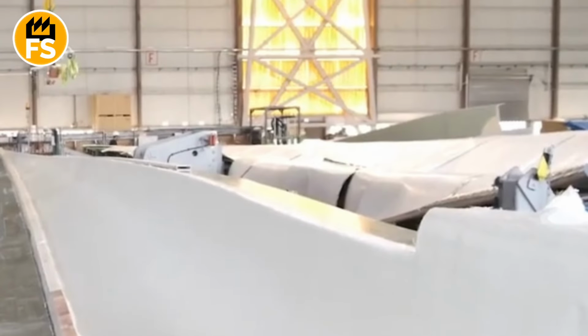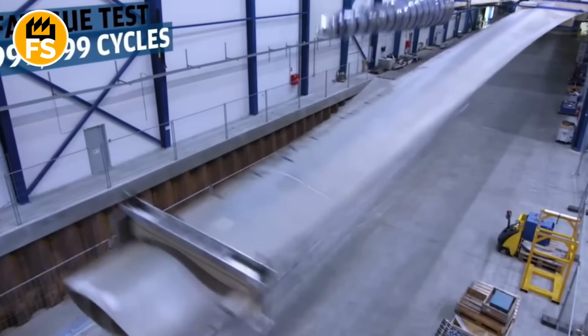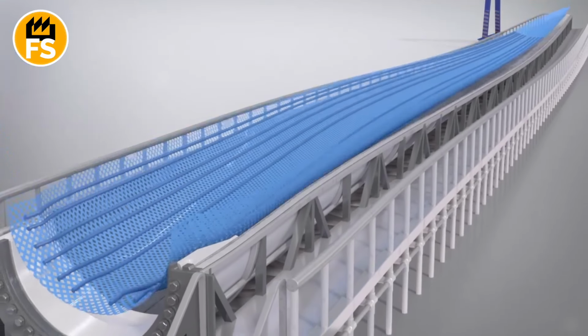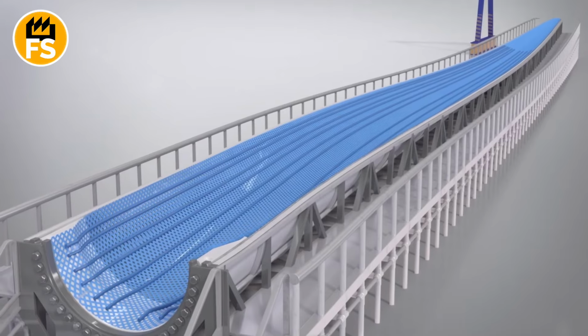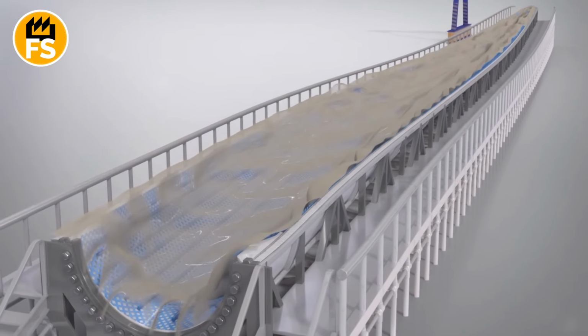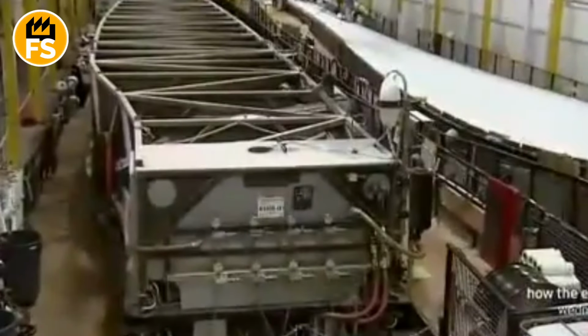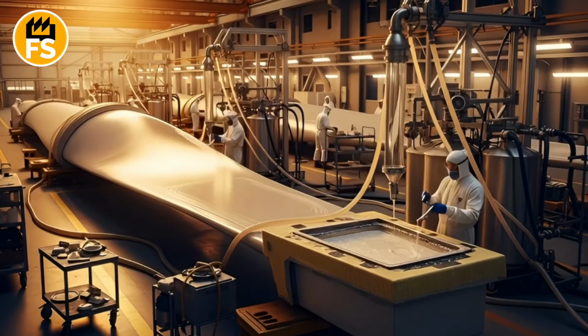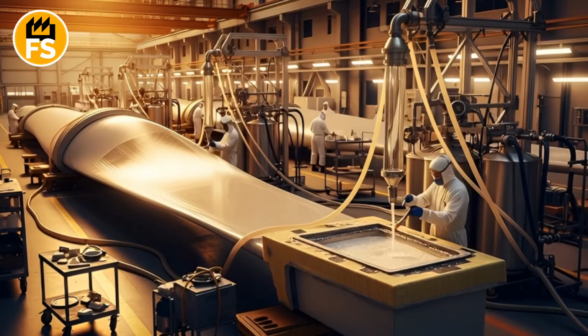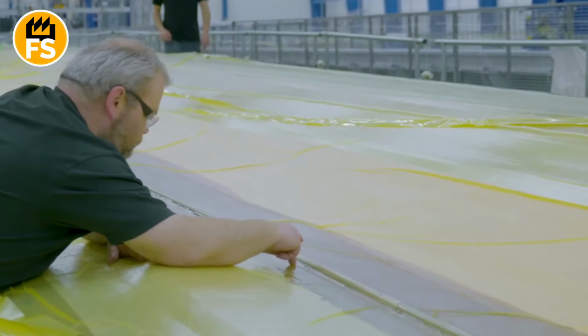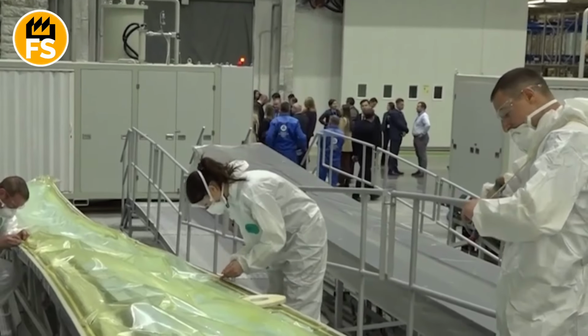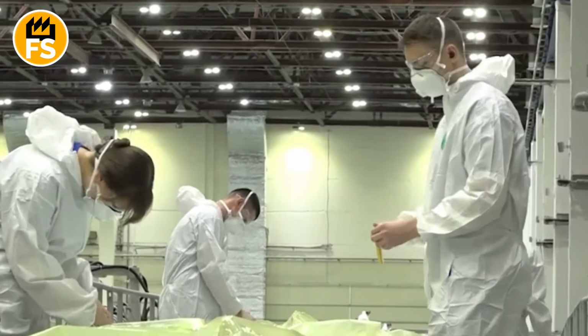The next step is laying fiberglass layers that form the blade's outer shell, as well as core material blocks. Fibers are typically laid by hand by experienced technicians, or using automated fiber placement to ensure proper fiber orientation that will resist predicted loads. After laying all the dry layers, the mold is closed and a deep vacuum is created inside. Resin, epoxy, or polyester is introduced into the mold, and vacuum pressure uniformly and completely impregnates all the fibers, displacing air and ensuring maximum density and strength. This process allows manufacturing large, nearly void-free structures with precisely controlled fiber-to-resin ratios.